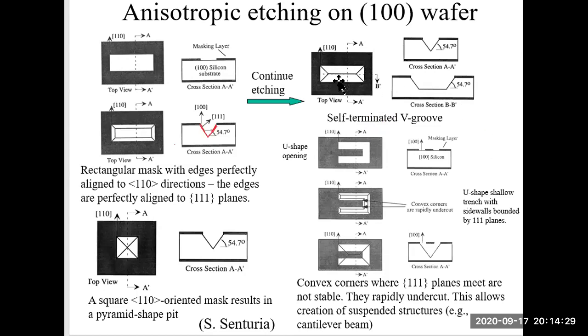Nothing will happen, right? Because now this structure is completely bounded by four 111 planes. The 111 plane serves as an etch stop, so the etch will be stopped. Even if you continue etching, this V shape will not change. We call this self-terminated. The etch will be terminated.